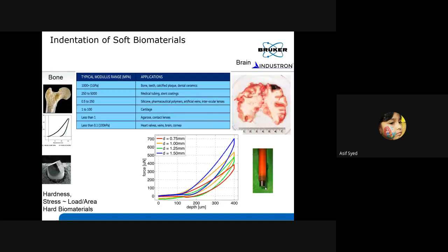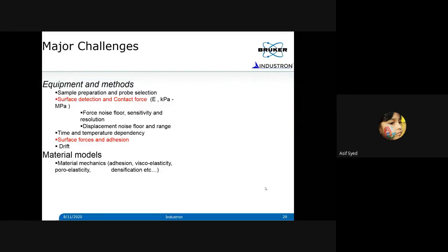One of the problems is, as you reduce to smaller and smaller length scales, the size of the probe, the contact mechanics and how you deconvolute the properties becomes a little bit complicated because various other things come into play. For example, adhesion. Okay, when you make the probe smaller and smaller, and the material is soft, you may not be able to even detect the surface of the sample. Those are all the things that I'm pointing out in my next slide.